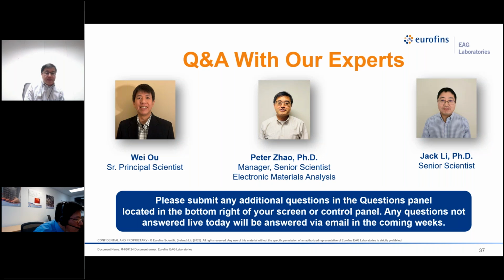Let me go back. Do you use silicon matrix standards or silicon carbide matrix standards when testing silicon carbide samples? Yeah, it's a very good question. As Jack already mentioned, the ion yield may be different in different matrices. At EAG, we always use the same matrix to quantify the silicon carbide or silicon. So we use silicon carbide standards for the silicon carbide analysis. For example, nitrogen and aluminum, the dopant or implant. We have nitrogen and aluminum in silicon carbide standards to quantify this.